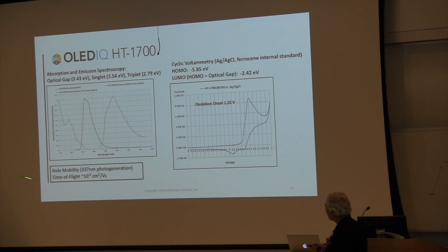The other things, we measure hole mobility using time of flight with photo generation. The mobilities typically are 10 to minus 4 centimeters squared per volt second, which is the same as the vacuum deposited materials.